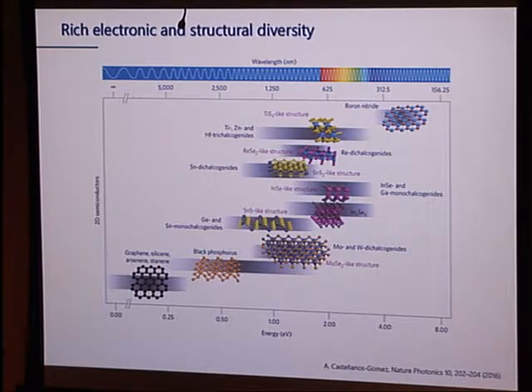These are amazing materials. If you look at their band gaps, they span anything from basically a semi-metal slash metal all the way to a high band gap insulator, boron nitride or hBN. And then in between, you have just about any band gap that you might wish to hit. Some of them are strongly strain-dependent, so black phosphorus has a slightly buckled crystal structure, and if I apply strain along one direction, I can dramatically change the band gap. And so there is actually a wide range of electronic and optical properties, which means that they are naturally made for, they're of high interest to try and make electronic devices with them.